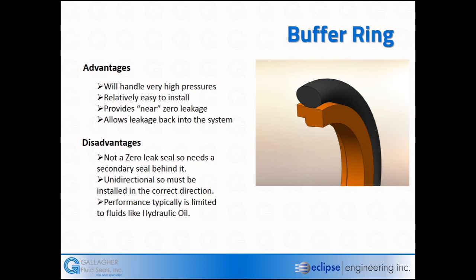And what that does is it will provide a zero leak seal on the backside, and in between the buffer ring and that secondary seal, there'll be a little bit of fluid which will keep the secondary seal lubricated. The trick to making this seal work is that the pressure in between the buffer ring and that secondary seal will be somewhere less than 100 psi. So that causes that secondary seal to perform for a very, very long time. Buffer rings like this will operate at 3,000 psi, and with backup ring systems will operate at much higher pressures, into 5,000 and 10,000 psi. Very high PV rates or very high cycle rates. So it's a pretty reliable system.